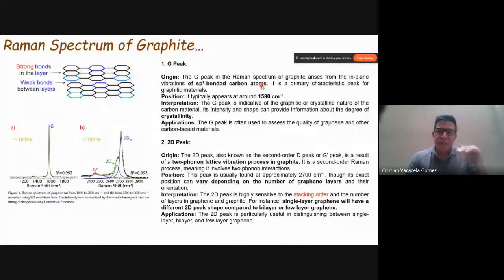Yeah, so the G peak gives this information about the sp2 bonded carbon atoms. If you have a narrow G peak, you have a good graphene. Why? Because it also gives information about the crystallinity. So you have a higher crystallinity if your G peak is very narrow. If you have a broad peak, of course, the crystallinity of this system decreases. The position of this peak is found more or less at this frequency. Of course, the application for this peak is to identify the presence of carbon materials and the crystallinity of the carbon material you have.